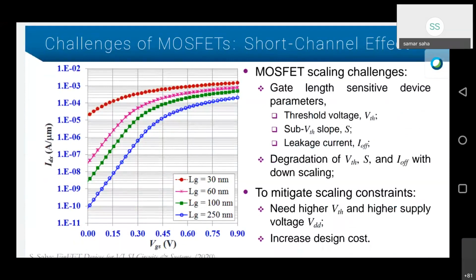The challenges. The first challenge: if we see these plots, the IDS versus VGS graph, this is plotted as a function of gate length. The bottom curve, which is blue, shows a gate length of 250 nanometers or 0.25 micron, and then goes up to 30 nanometers. This is taken at VDS equal to 0.9 volts, so this is actually the saturation region. The bottom curve shows that I off is about 10 to the power minus 10.